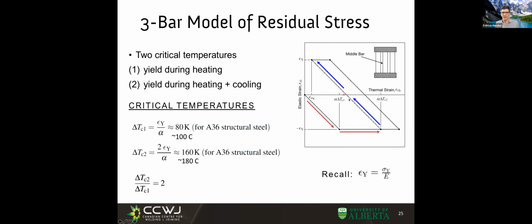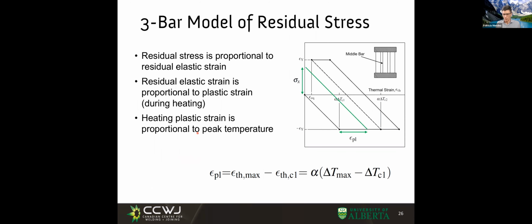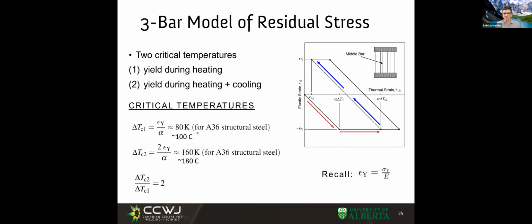What I wanted to bring up is there are two important temperatures. One is during heating, the temperature at which it starts yielding in heating, that we call delta T C1. And this is more or less 100 degrees. So when you are welding and you see 100 degrees, the material starts to yield. And then there is another one: if you put enough plastic strain during heating, when it cools down it will eventually reach yielding too. That is the temperature at which we would start having yielding during cooling, we will call it delta T C2. And that is of the order of 180 degrees C. And the final stress in this part will be a tensile stress of the order of yield stress.